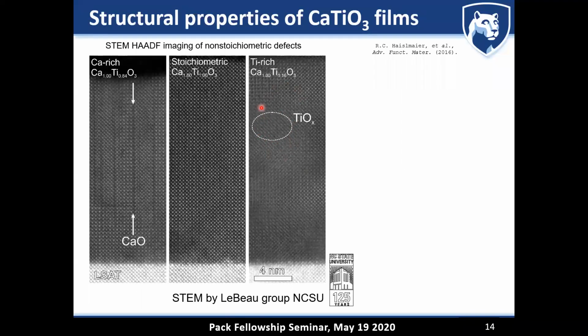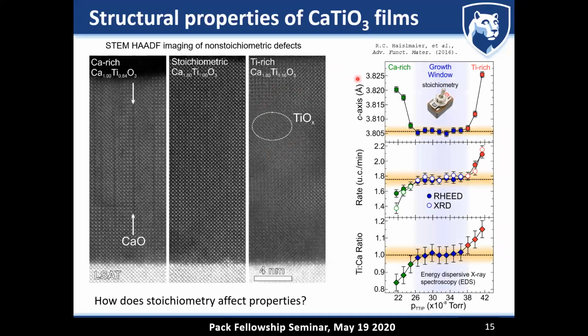They typically come because there are stacking faults, there are A sites that are basically missing, and they detune the position of the TiO6 octahedra, and it gives rise to this smeared-out image that you would see in scanning transmission electron microscopy. So, to make a long story short, what I'm showing you here is that we could control the stoichiometry, and what we find is that depending on the flux of this titanium-containing metal organic precursor, we could enter a regime where we maintained the stoichiometry as measured by the out-of-plane lattice parameter of the film.